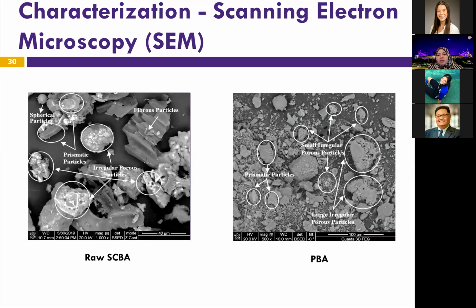This is a quick picture showing backscattered electron images from SEM for both the raw sugarcane bagasse and the processed bagasse. The raw bagasse ash, as you can see, contains unburned fibrous particles, like you can see right here. By contrast, the processed bagasse does not contain any fibrous particles. They are similar, in that you can see prismatic and irregular porous particles in both the raw bagasse ash and the processed bagasse ash. However, these particles are finer in the processed bagasse ash. Presence of these prismatic particles is attributed to crystalline silica, while irregular porous particles are amorphous silica. We want to increase the amorphous silica as much as possible in the processed bagasse ash because that's what's going to make it more reactive in terms of cement replacement.